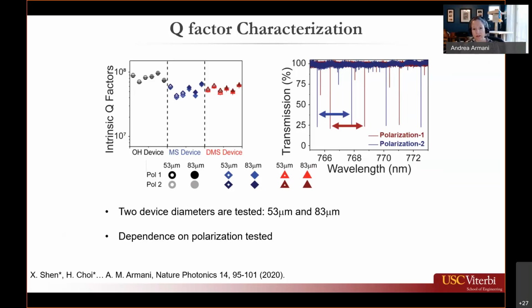And we measured the quality factor at both polarizations. As you can see in the data, the polarization was not playing a role, or at least not a significant role, in our quality factor measurements. Additionally, the device diameter wasn't playing a significant role in our quality factor measurements, and both of these statements you would expect to be true. Additionally, the surface chemistry wasn't significantly changing our quality factor. So all of our Qs were in the upper 10 to the 7 range, which means we can directly compare the devices because they all have very similar quality factors.